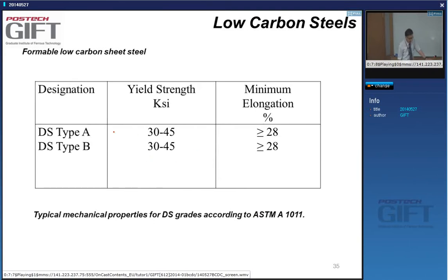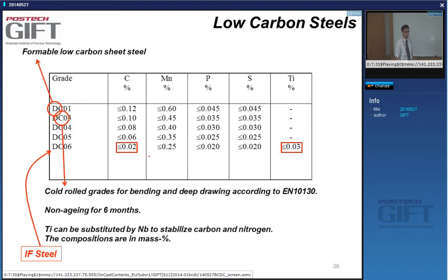And these are typical values in terms of the yield strength. If you want to know values, you have to multiply by about 7 if you want equivalent megapascal values, so that would be 200 to 350 megapascal. Okay, so comparable to what the European norms give.